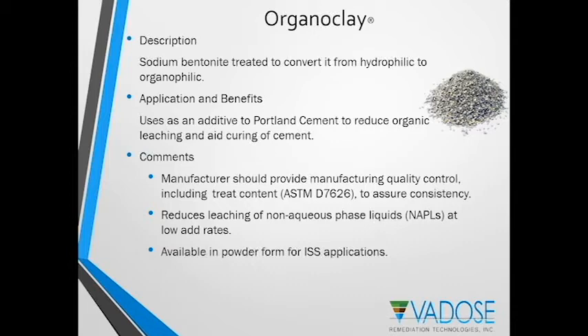And so therefore, when it's used as an additive with Portland cement, it will reduce the leaching of those organic contaminants from a stabilized or solidified mass. The manufacturers are able to provide quality control documentation on this material. There is very good data showing its ability to reduce leaching of non-aqueous phase liquids at relatively low addition rates, say 2 to 4%, and it is available in a powdered form. One other comment about that, there are in fact models for predicting leachability of these organic contaminants from solidified mass when Portland cement and organoclay are used together.